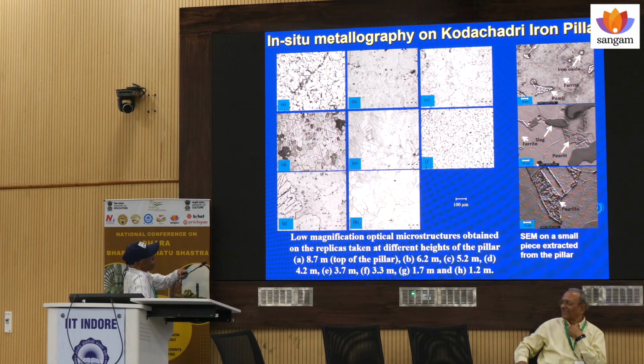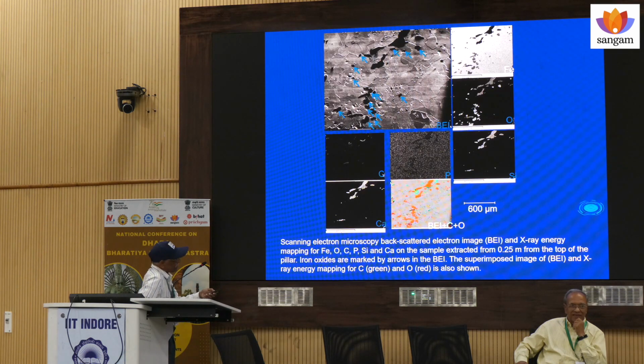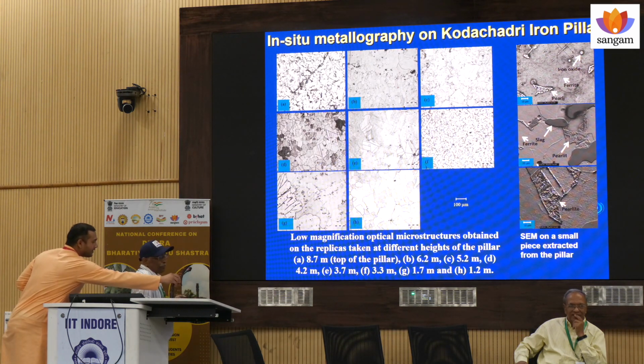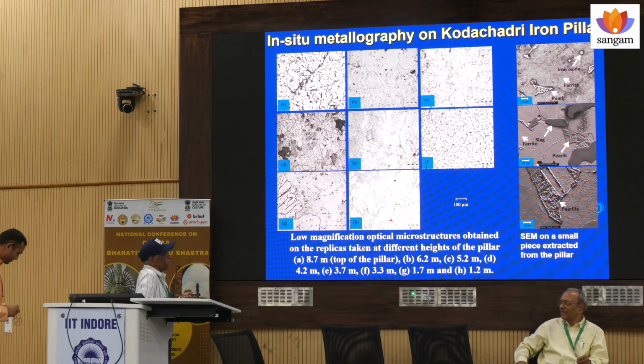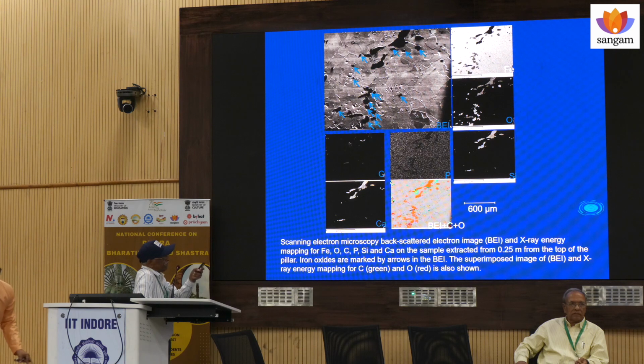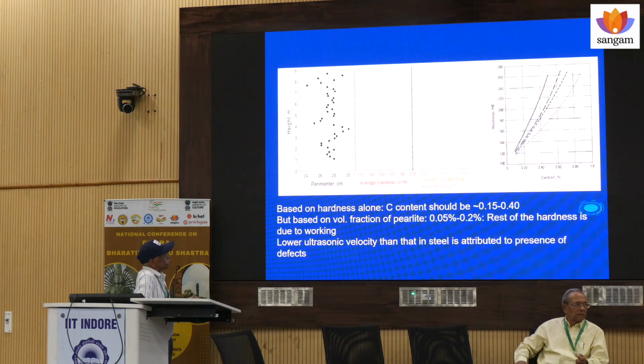So here also the microstructure varies quite a bit, and it also has ferrite and pearlite structures. And here we have also taken a small piece from this pillar because it is too much rusted, and you can take some piece out by hand itself. Then we did the investigations, various elemental analyses, and you can see that there are some carbides, that is cementite, and also calcium based slag inclusions. So this is again a ferrite pearlite structure with slag and also the carbide precipitates.